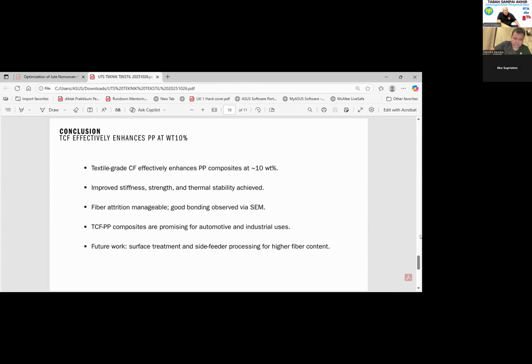Next one is that the fiber not only improves the stiffness and strength, but also enhances the composite thermal stability. It could stand higher temperature before degrading. However, higher fiber content like 15% leads to diminishing returns due to fiber agglomeration and uneven mixing. From the microscopy result, we also learned that fiber matrix bonding was excellent, especially at the optimal loading, with the fiber breaking rather than being pulled out during the testing. So the key takeaway is that textile grade carbon fiber polypropylene composite offers a cost effective, lightweight still, and strong alternative to traditional composite, particularly for the automotive industry, where cost, weight, and performance must be balanced.